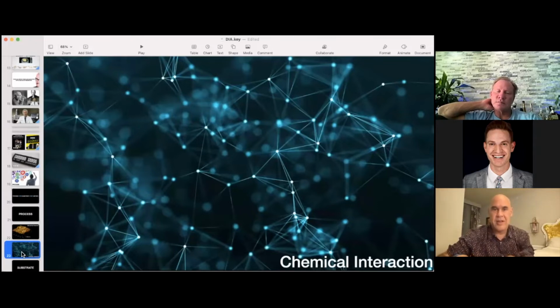Chemical interaction. Some people like to get caught up in the semantics. Listen, it's chemical interaction. So how do you generate chemical interaction on the enamel after it has been etched? You use a dental adhesive, whether it contains MDP or another organic functional monomer. It doesn't really matter. What matters is that you need to use a dental adhesive on the enamel, and you are going to generate chemical interaction, and you're going to generate that mechanical interlocking.